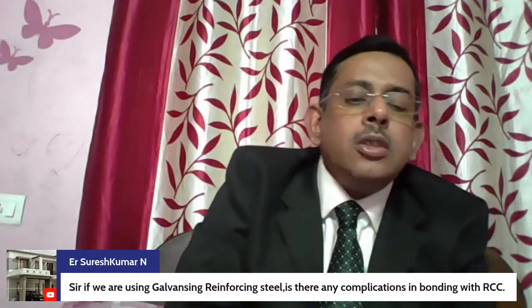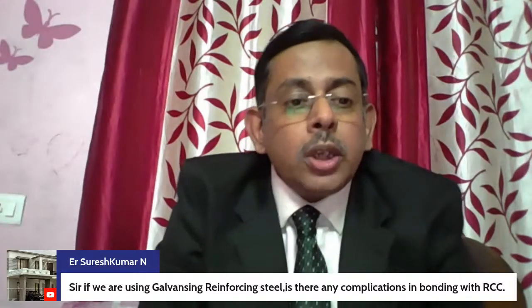During welding you will have some zinc fumes, so from a safety point of view you must be covered enough so that you don't inhale zinc fumes. Once the welding process is done, you need to re-galvanize that place by zinc painting or spray painting, because you cannot leave that place bare. Your adjacent areas are galvanized steel, so you will have a two-material concept there. One is zinc, another is steel, and that place will have rapid corrosion if you don't protect it.